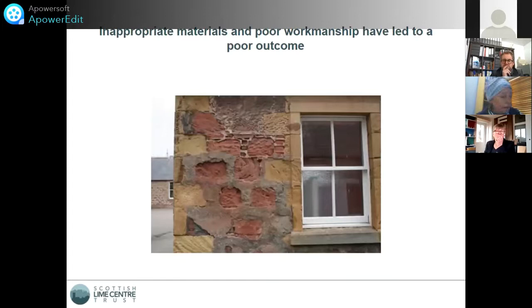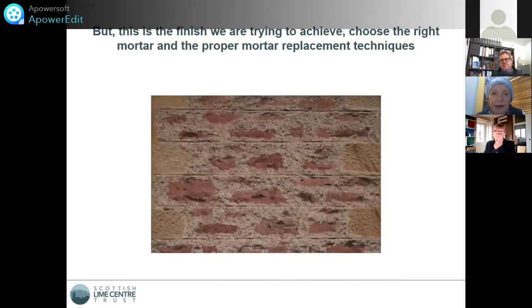And you can see in this shot here, inappropriate materials have been used with very little regard to the finish, poor workmanship, and have led to a very poor outcome. And this is a shot of the wall just right next to it. If we were going to repair this, this is what we're going to try and achieve. So it's got a particular texture and colour, the mortar, so that's where our mortar analysis service can come into its own, so we can match mortars much more closely using matching aggregates. And you'll see that the mason has lined out the masonry in line with the quoin stones or rybats to make what is very informal rubble infill look slightly smarter than it really is.